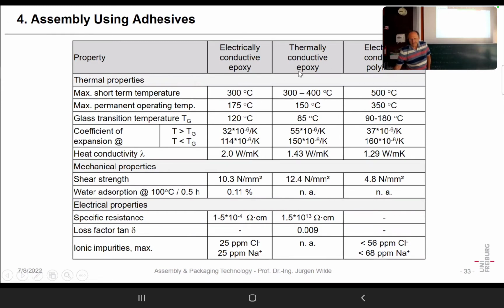Here was some data, maybe also from company information. For very short time, they even gave 300 to 400 for thermally conductive epoxy. For the 400, I doubt. Here for the polyimide, they say 500, but short time really means only seconds. Here for the epoxy, they give 175, or even 150, as maximum permanent operating temperature, and for the polyimide 350.